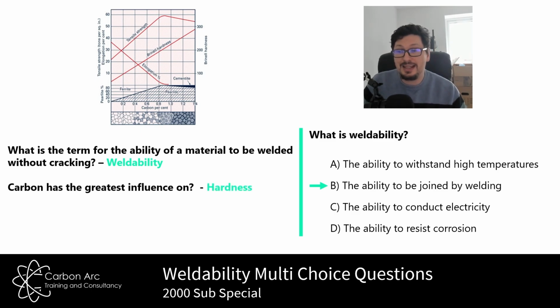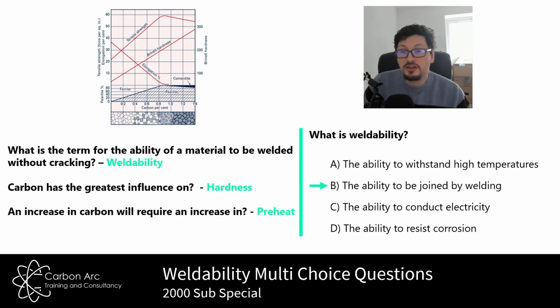Carbon has the greatest influence on hardness, right? Strength is always there because we add carbon to the system in order to give us strength. But really, we're worried in weldability about the hardness value of that grain structure that it produces. And then an increase in carbon will require an increase in preheat. So by far the biggest control we have here is as carbon content goes up and weldability comes down, we increase the preheat value to get more heat into the structure, so it cools slower and therefore is less likely to crack.